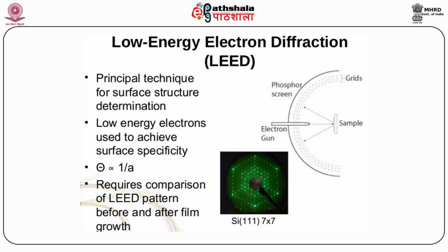Due to the very strong interaction with matter, electrons have a mean free path of the same order as the interatomic spacing. By measuring a diffraction pattern for a certain energy of incident electrons, the periodicity of the surface lattice may be determined by the kinematical approach. One of the main assumptions of the kinematical approach is that the incident electrons scatter in the crystal just once. This assumption is often not fulfilled, but the kinematical theory describes the diffraction pattern well.